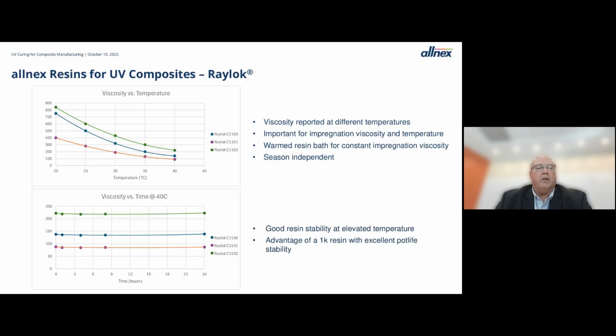And you can see, even though they may start a little bit higher than what we normally want for a composite formulation to get good fiber wet out and good infusion, if you just ramp the temperature up a little bit to, say, 35 or 40 degrees C, the viscosity drops precipitously, and you get nice low viscosity for good fiber wet out and good infusion.